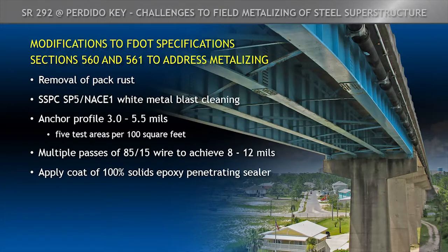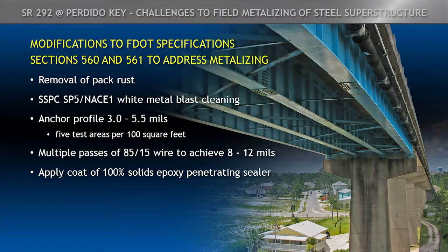That included the removal of pack rust. We also increased the level of surface preparation to SSPC-SP 5 / NACE 1 white metal blast cleaning for the metalizing. And we asked for an anchor profile of 3 to 5.5 mils. We were very clear that that anchor profile had to be angular and dense so that the metalizing would mechanically adhere to it. And we did testing at 5 tests per 100 square feet for the anchor profile. We asked for the metalizing wire to be 85% zinc and 15% aluminum.